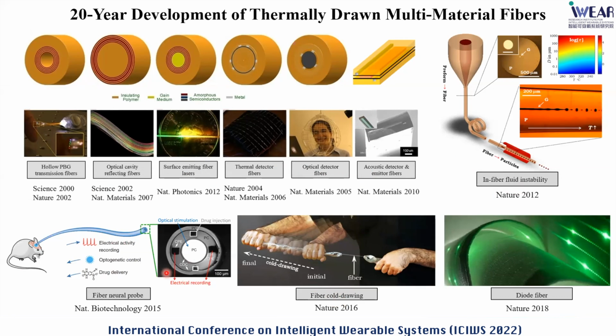We can also use this fiber to interface with the neural network. And recently, we demonstrated that we can form this kind of in-fiber package, to encapsulate chips into the fiber. So those are the demonstrated results. However, there is one major limitation, which is the material selection for this process.